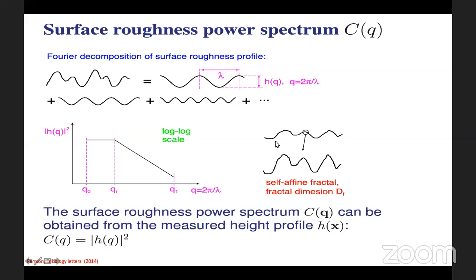I will talk about fractal dimension. Suppose you have a surface roughness, and if you magnify this surface, you will have a surface similar to that, but having higher height amplitude. In this case, the fractal dimension will be more than 2. But if this profile has nearly the same height amplitude as the previous profile, then you have a fractal dimension of approximately 2.